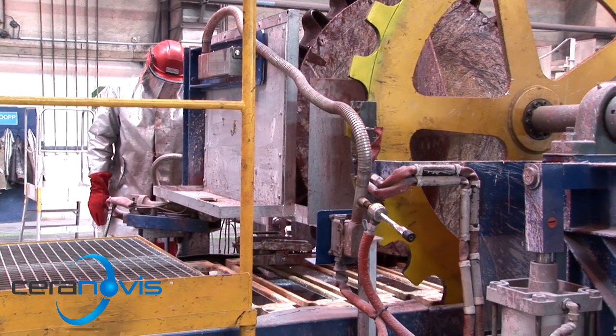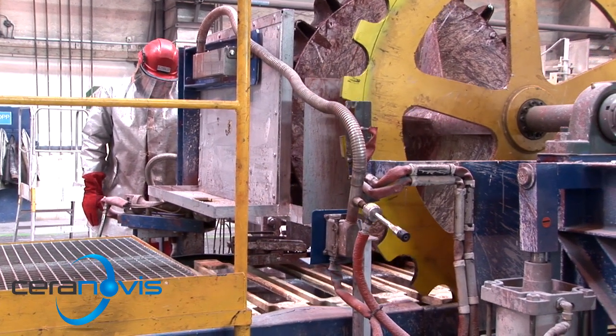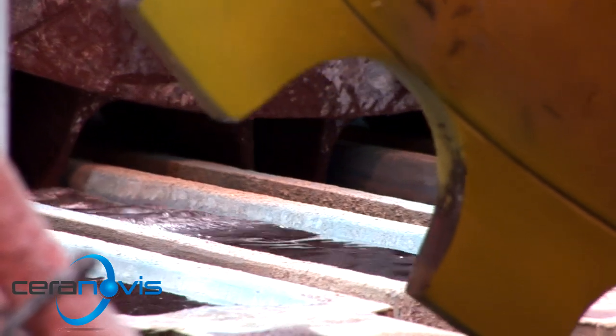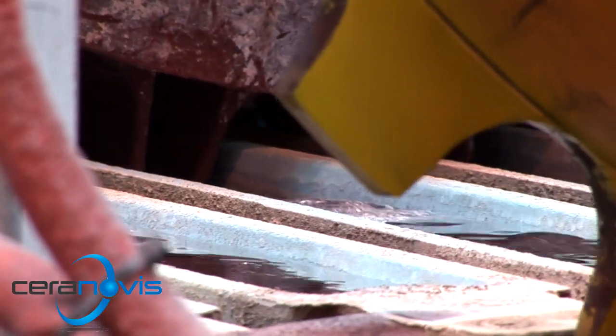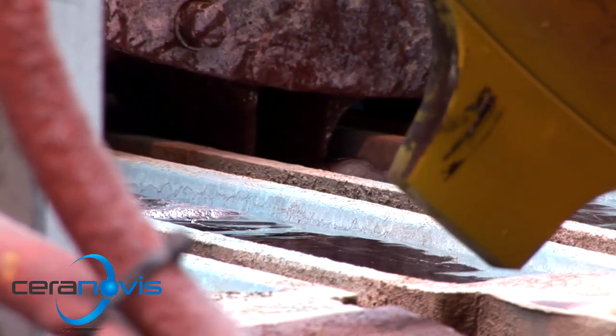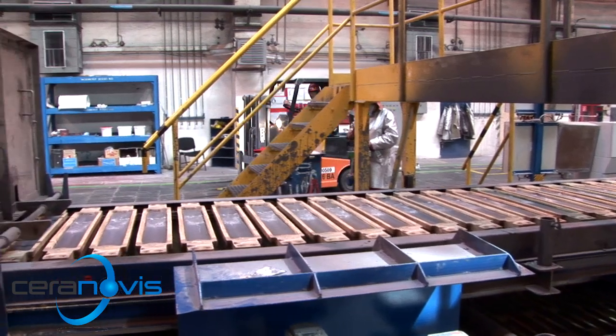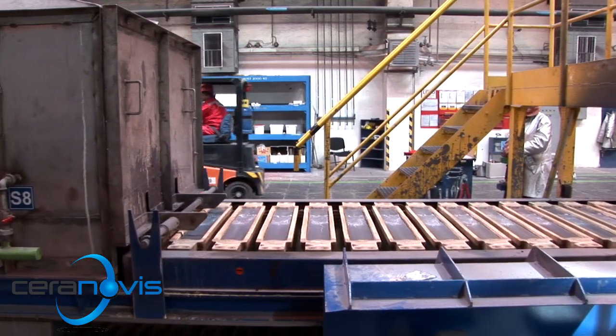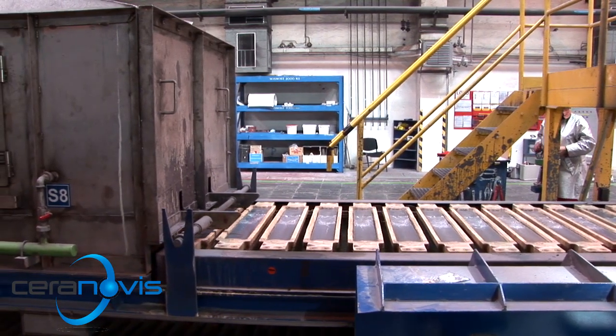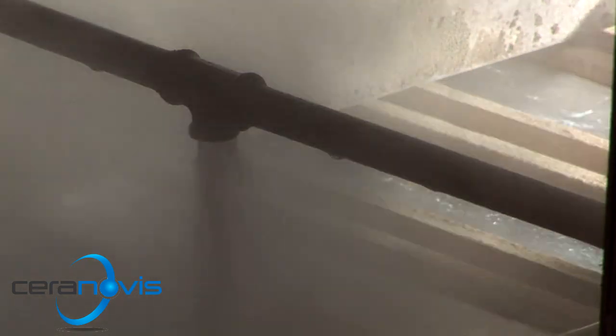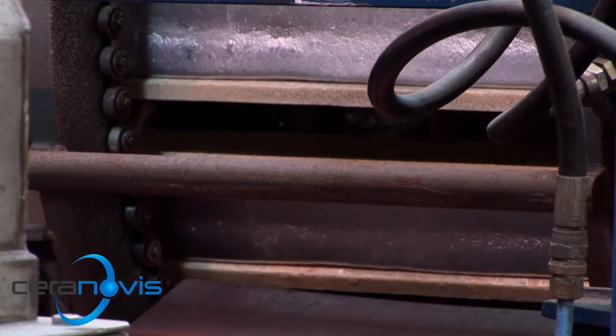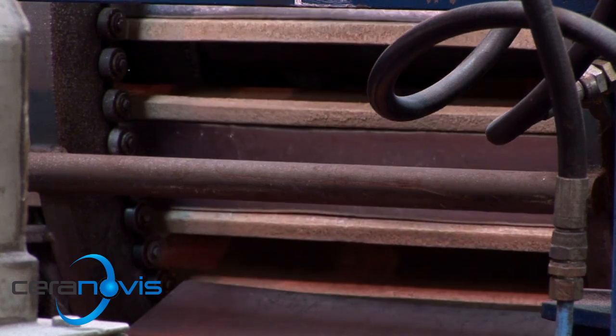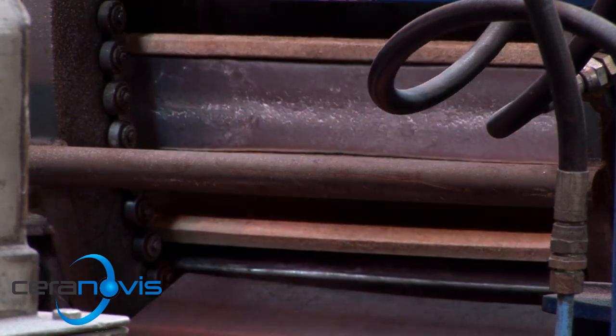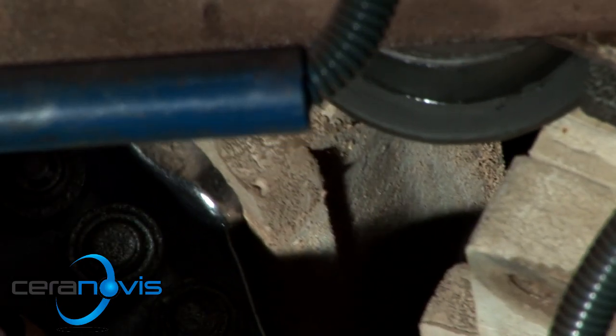During production, the applied coating must sinter into a ceramic layer at a mold temperature of at least 350 degrees Celsius. This is an absolute must. If necessary, the active cooling must be managed to achieve sintering during the first castings. After sintering, the product is completely resistant to temperature shock and water cooling. The coating has good demolding properties and its excellent separating characteristics protect the die.